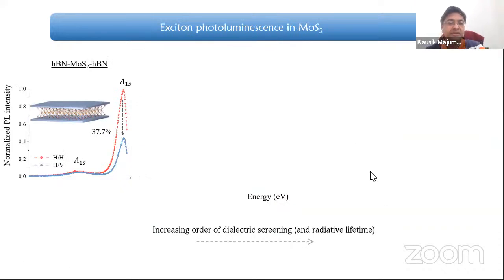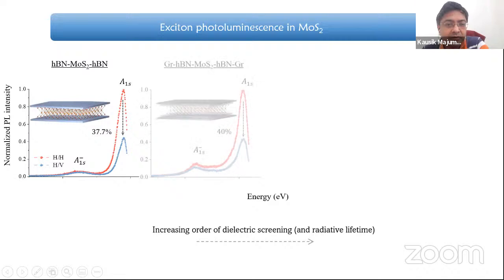So these are the experimental data. First we have an hBN encapsulated molybdenum disulfide flake, where we achieve 37% valley coherence. Here we are exciting close to the 2s state, so we don't degrade the polarization because of scattering from the higher energy states. Not much on the hBN encapsulated one, but later I'll show that.